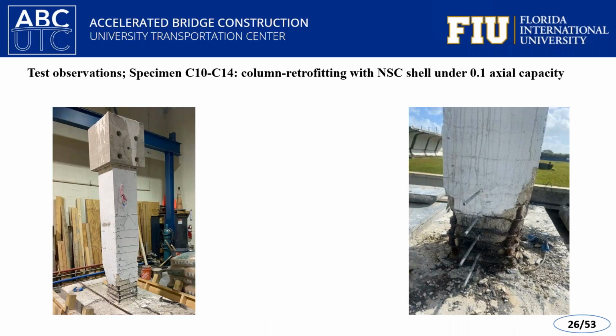This figure shows crack pattern and failure mode of specimen C10, C14, which was retrofitted using normal strength concrete jacket. Compared to the control specimen C10, this specimen exhibit increased stiffness and strength. However, under cyclic loading, failure eventually occurred due to buckling of the longitudinal corner rebars within the jacket. Crushing was mostly limited to the jacket region, as you can see.